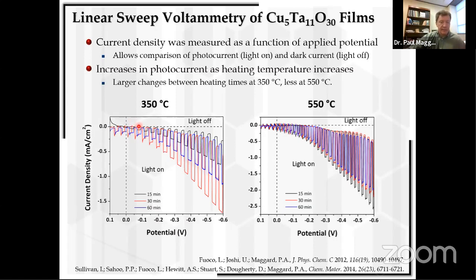When the light is irradiant on it, we see a photocurrent. And when the light is off, no photocurrent. We can measure current density in milliamps per centimeter squared of surface area of the film. We see a current density of around 1.5. For N-type oxides, the most efficient ones, which have efficiencies of 10, 20%, you want to get up to around 20 to 25 milliamps per centimeter squared. For P-type oxides, which is what these are, it is very difficult to get high current densities like this. And so this was surprising and nice for us.